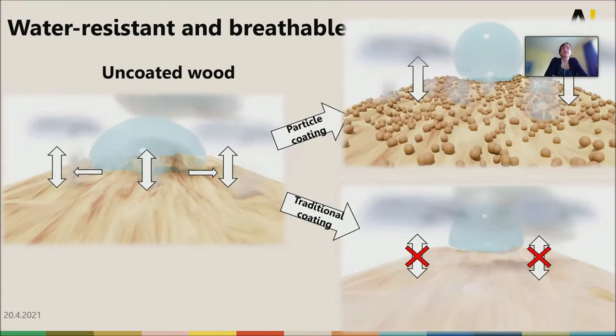The water resistance works on a similar principle to what I showed for the wax particles. If we have the uncoated wood, then the water will both penetrate the wood and spread on the surface. This illustrates the water vapor, which also goes through and comes out again in the uncoated wood. But the problem is that we usually want to protect the wood from liquid water. We want to protect it from stains and such things. And then we can use this lignin particulate coating.